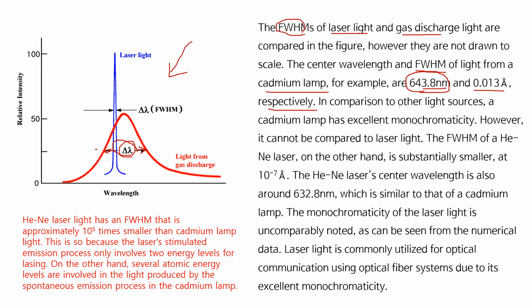In comparison to other light sources, the cadmium lamp has excellent monochromaticity because the FWHM is just 0.013 angstrom, so a very narrow bandwidth. However, it cannot be compared to laser light. The FWHM of the helium neon laser, on the other hand, is substantially smaller at 10 to the minus 7 angstrom, compared to the FWHM for the cadmium lamp.